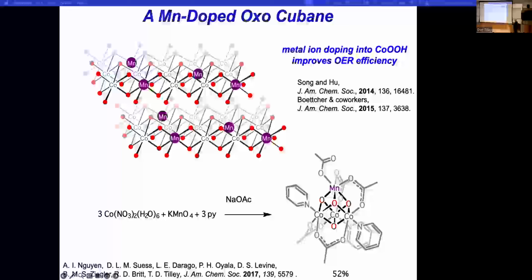And in fact, mixed metal oxides are known to be better in many respects for a reaction like oxygen evolution, water splitting. That's seen, for example, in doping manganese into that layered cobalt structure. That gives a catalyst that has a lower overpotential and it's more efficient. So how do we get manganese into the cube? Well, Andy came up with this idea to just start with three cobalt twos and permanganate, and everything should assemble with the permanganate giving the four oxygens in the cube, and it works.